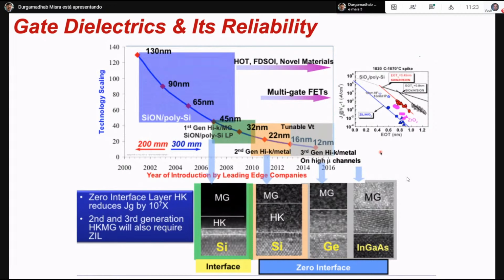So that actually started the high K dielectric research in around 2000. And then around 2007, in the 45 nanometer technology, they first introduced the high K dielectric. It was very challenging in the beginning, but it showed a very low leakage current, as you can see in this leakage current, and drove the EOT, the equivalent oxide thickness, to below 1 nanometer while limiting the leakage current.